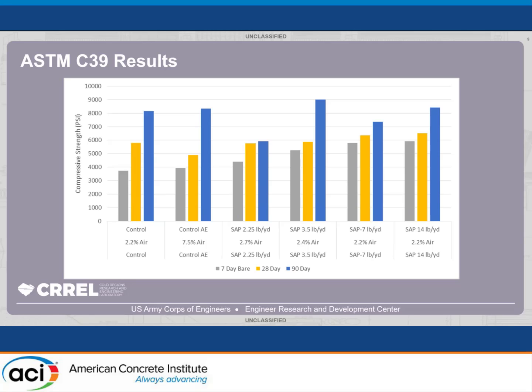Moving forward into some of the results, these are our compressive strength results. Moving from left to right, that's where our controls were. As you can see here, as we added more SAP, from left to right, 2.25 pounds per yard all the way up to 14 pounds per yard, you can see that the strength at 7 days especially is gaining over time.